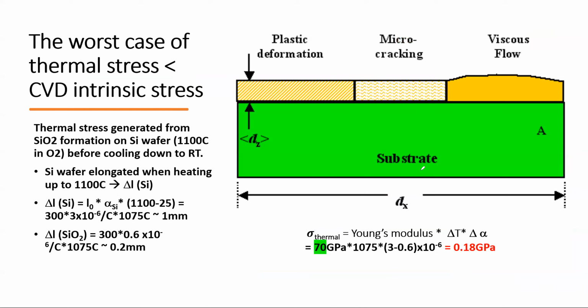And if you see the case I presented here about SiO2 formation, usually if it's done right and the SiO2 is not too thick, you have plastic deformation, because SiO2 is soft compared with silicon. The Young's modulus of SiO2 is about half of the silicon. And in some cases, if you go too thick, then you start to generate micro cracks.